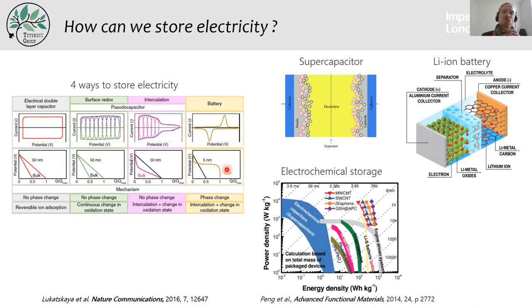The second line here corresponds to galvanostatic charge discharge. So here, instead of controlling the potential on the terminals of the device, we control the current and we measure the potential. And that gives us for the supercapacitors a linear correlation, and for the battery, a plateau. So why does the supercapacitor have a rectangular CV? It's because of the electrolyte that is placed between the two electrodes. Upon polarization of the device, the ions in the electrolyte are going to diffuse towards the surface of the porous electrode and adsorb onto the surface. And this process is very rapid and should not depend on the voltage of the device. And that's why you obtain this rectangular shape.